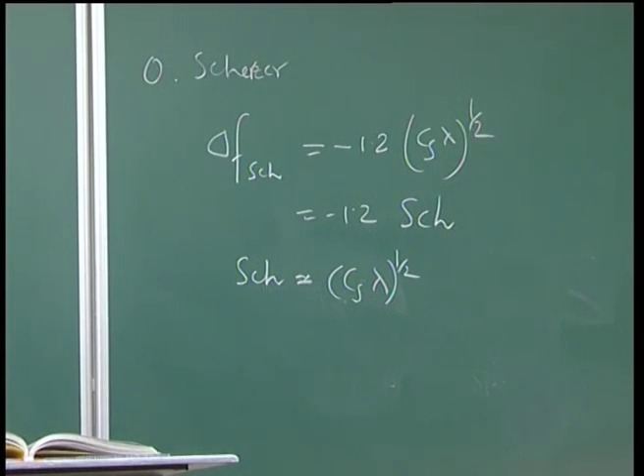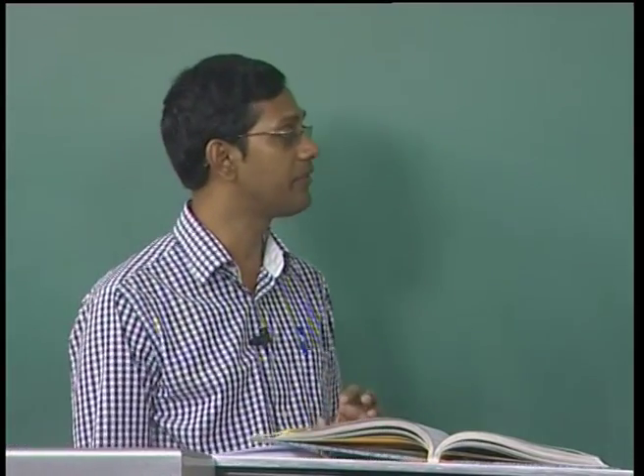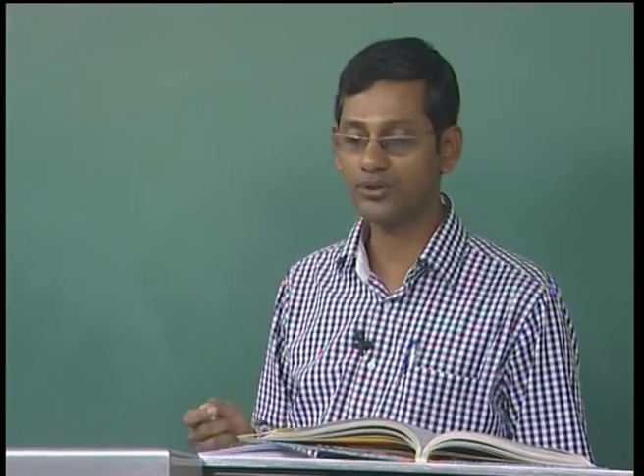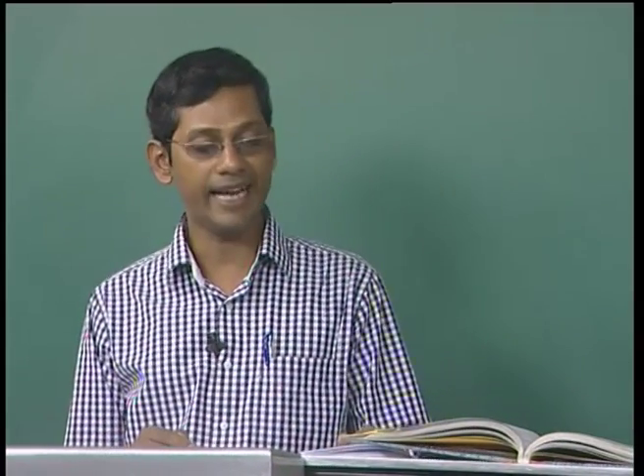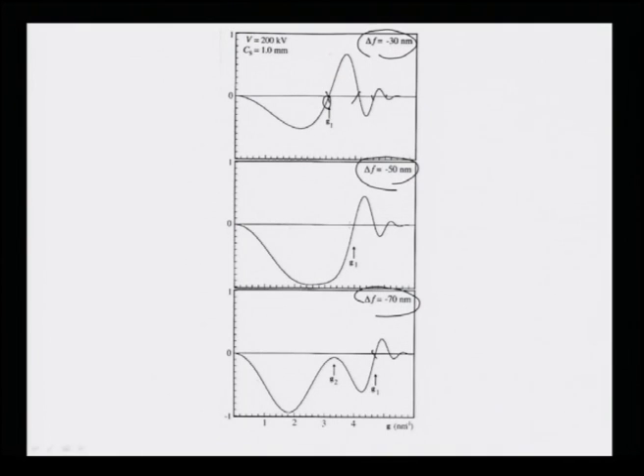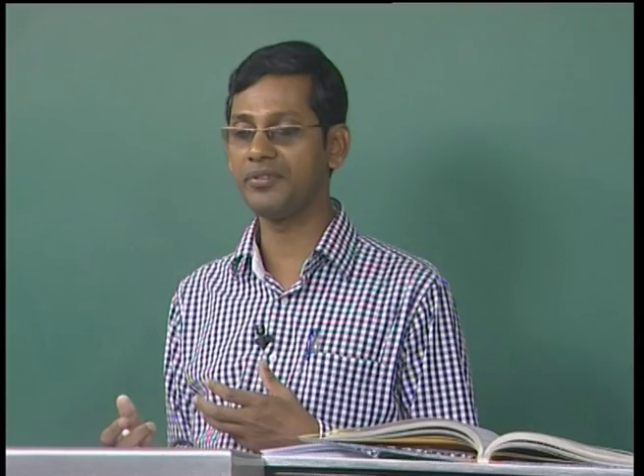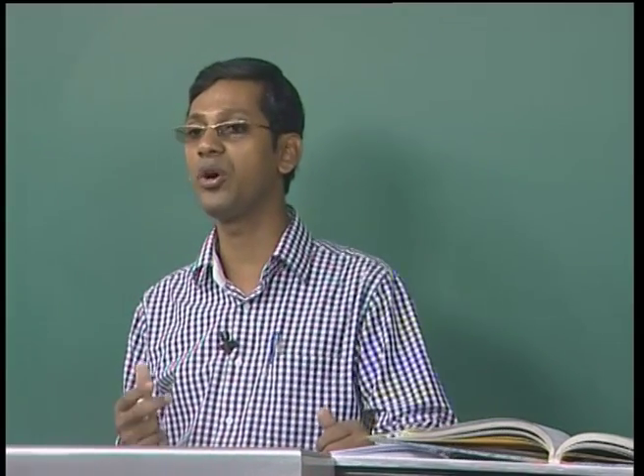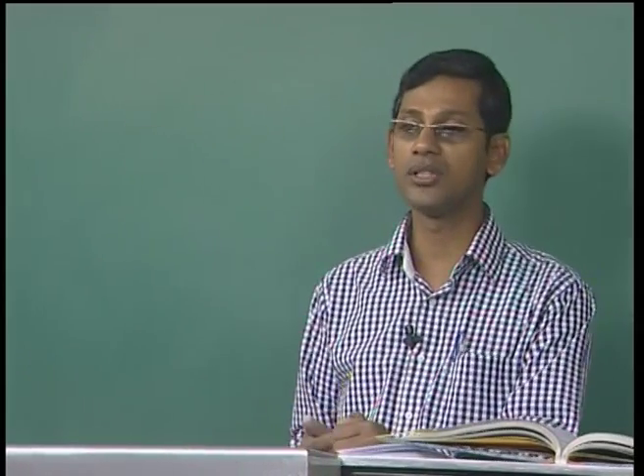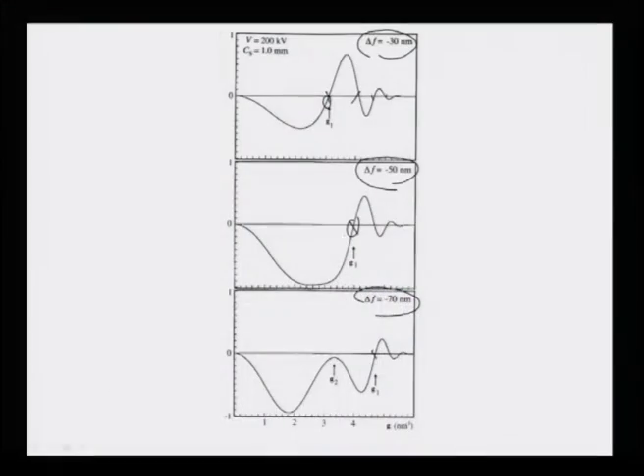What you can see clearly from this picture is that the Scherzer focus tells us that all the beams will have, at this defocus, nearly constant phase out to this first zero, the first crossover on the zero g axis. That is what is shown here. So all the electron beams will be of nearly constant phase out to this, and this is what is required to obtain the best possible resolution or information in electron microscopes. The best performance will obviously be expected from a microscope at the first crossover value on the g axis.